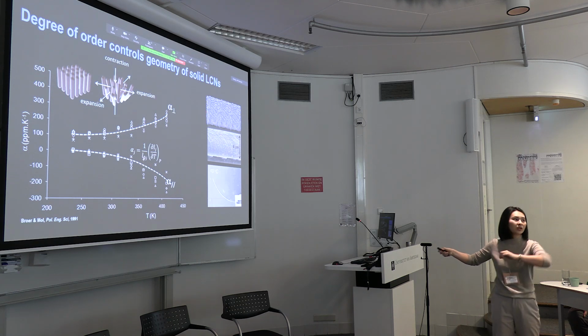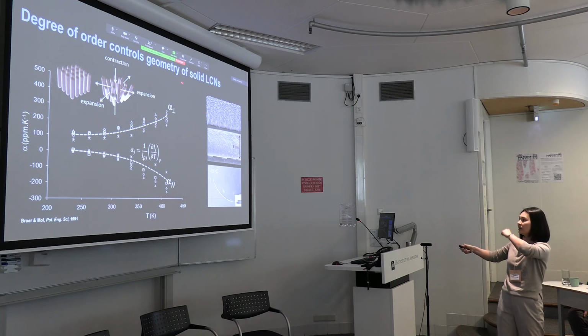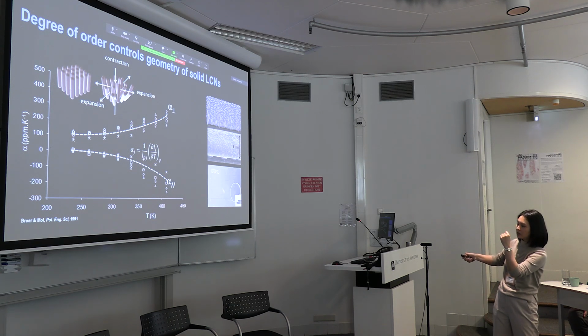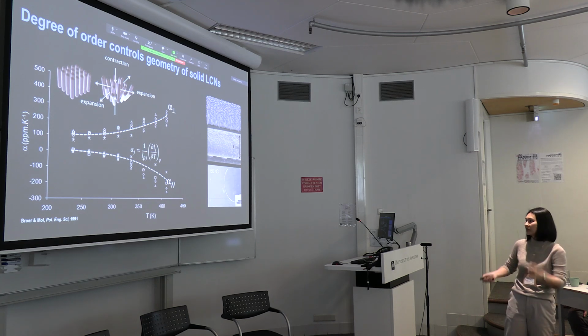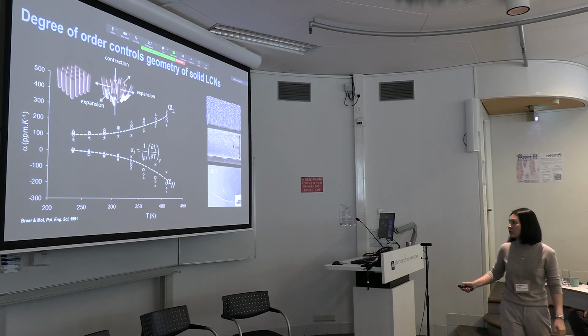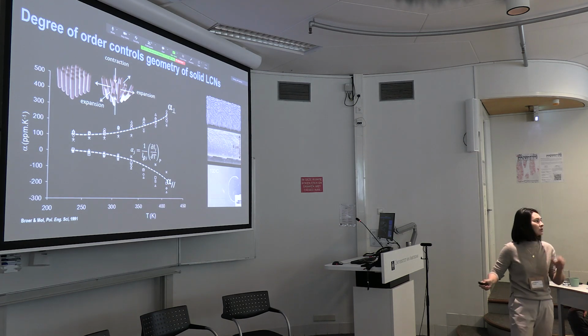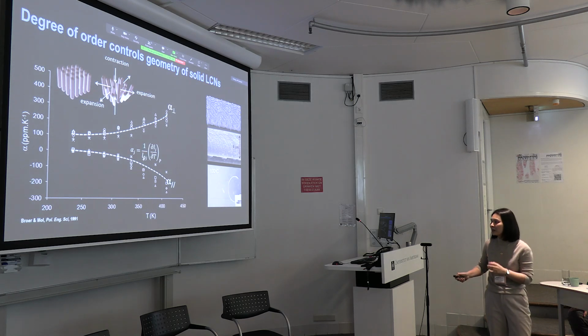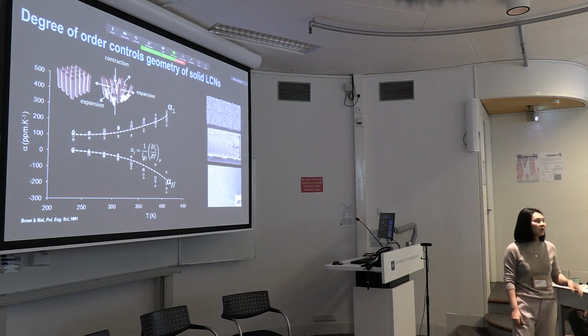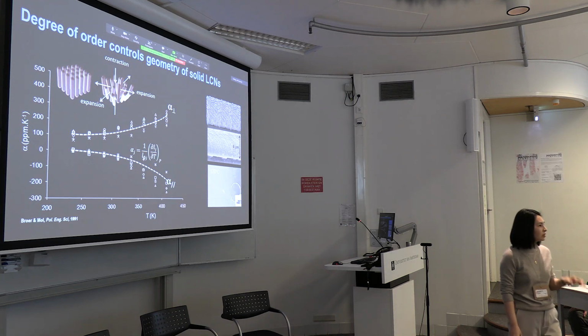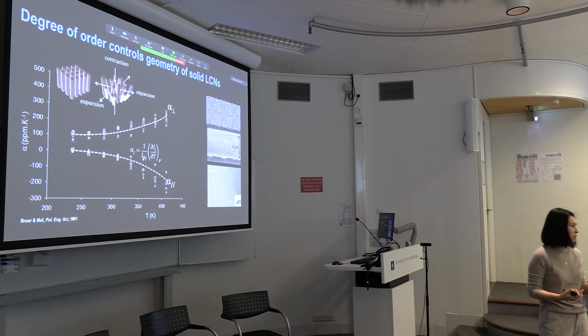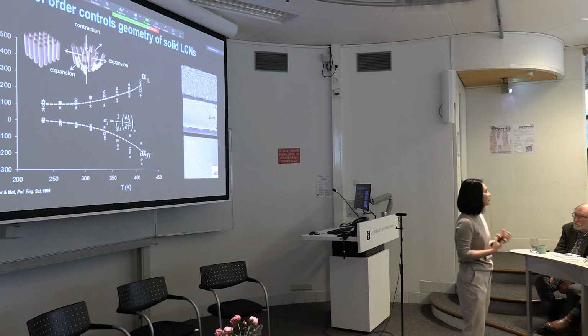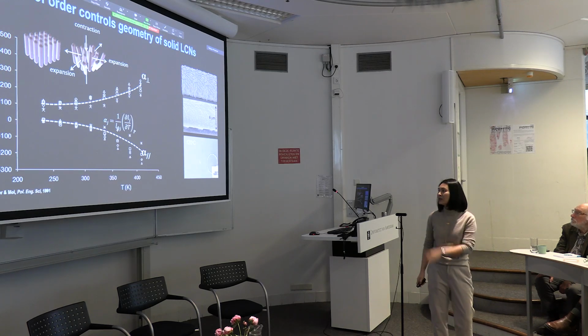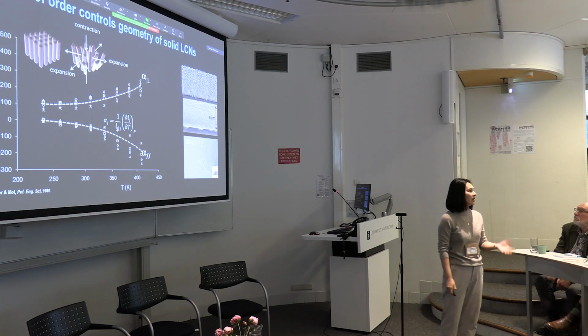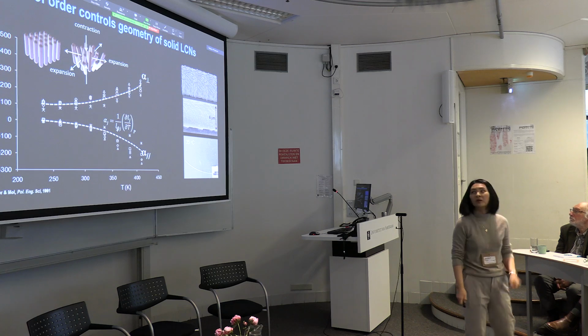On the top, the molecules are organized parallel, and they start to rotate until the bottom ones are perpendicular to the substrate. What happens is that when you heat it up and decrease the order parameter, it starts to bend because the top contracts and the bottom expands. And this can happen in just one single film. Normally you need a bilayer structure, two layers with different thermal expansion coefficients, but in this case you can realize the bending within one film.